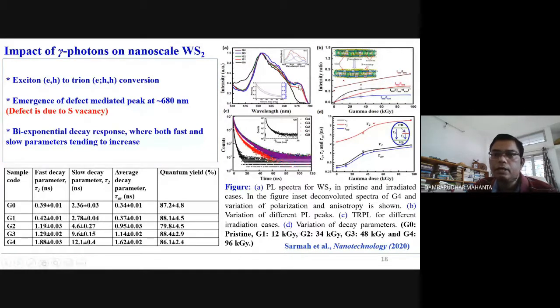manifestation in the spectra. The first peak we assign to near band edge emission or simple excitonic luminescence, which is around 610 or so. The second one we ascribe to trionic peak. So trionic peak is EEH or EHH. In this case, we believe that it is EHH. And along with these two, in addition to these 2 peaks, when there is an asymmetry in the peak, in the spectra, you believe that there is possibility of another peak.